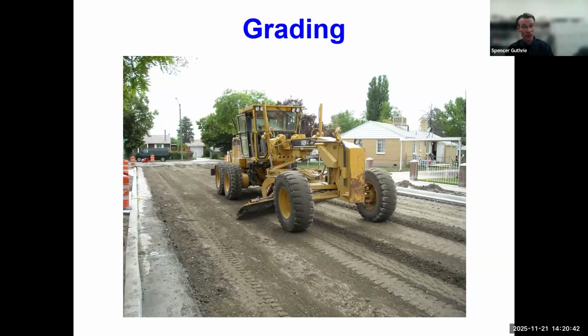The next step would be final grading. So at this point, our efforts are to ensure that we have a good cross slope, good longitudinal slope, enough space against the lip of the gutter, left and right, to ensure that we have room for the appropriate asphalt or concrete thickness, and make sure it's done, graded, in other words, before the cement begins really setting up.